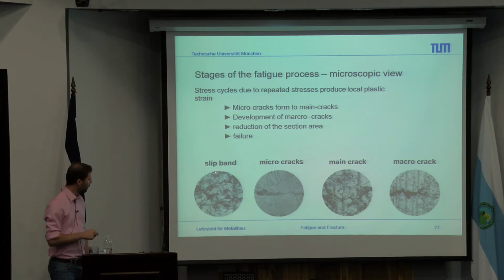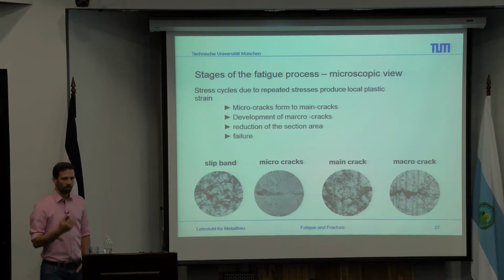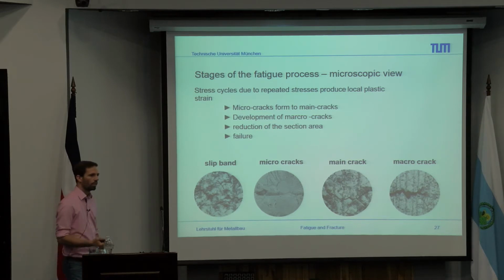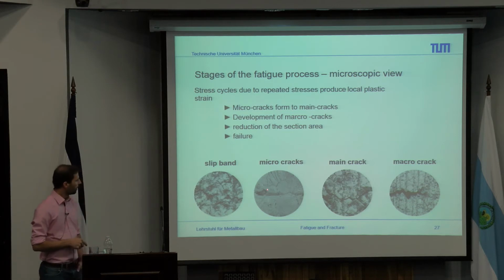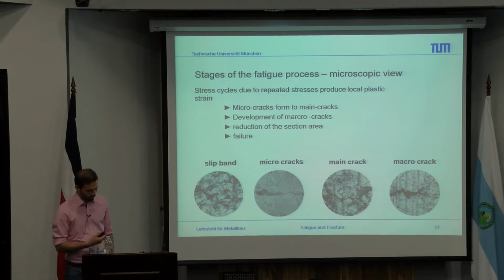So in the material itself, it looks like this. We have some slip bands, which you can see here at this part. This is just some local deformation of our material. Then we get some micro-cracks, which you can see at some parts here and there. Then we get some main cracks, which are here in this part. And at the end, we have a macro crack, which is quite huge and has here the crack tip, which we're going to talk about tomorrow.